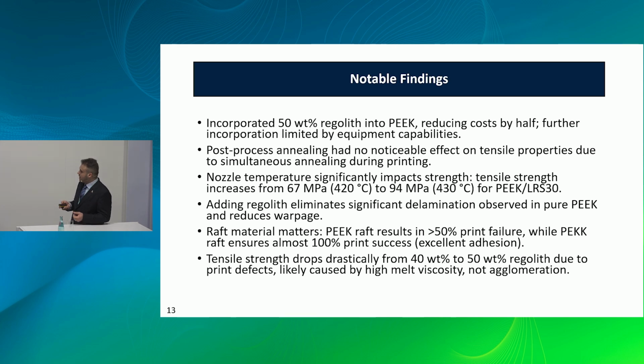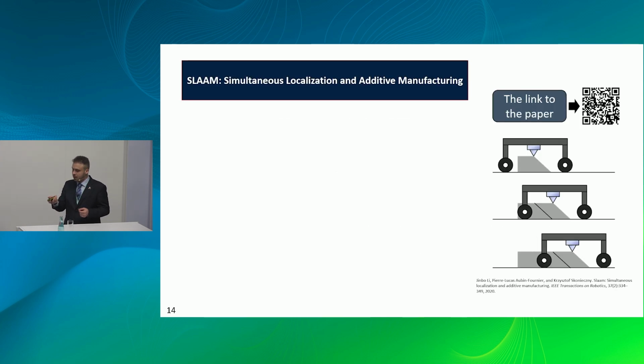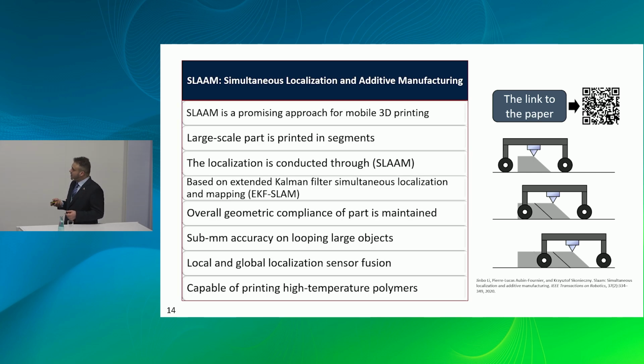And tensile strength drops drastically from 40% to 50% due to the print defects likely caused by high melt viscosity, not agglomeration. And this is another contribution by our lab about the robotics aspect. SLAAM is a promising approach for mobile 3D printing, in which large-scale parts are printed in segments.